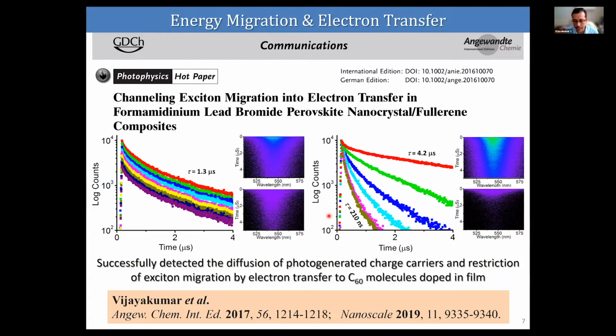Generally, in the excitation energy migration, either the excitons are moving, or in some cases, these excitons are separated into charge carriers and they are moving. And it is possible to restrict this diffusion of the charge carriers, as well as the excitation energy migration, by doping these films with fullerenes or fullerene derivatives. And efficient electron transfer is possible from the perovskite nanocrystals to the fullerene derivative. And we published this work in 2017 in Angewandte Chemie and in Nanoscale in 2019, so interested people can read those papers.